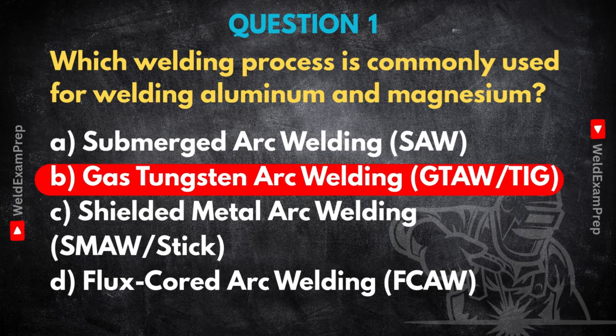Plus, for these reactive metals, that inert gas shield, usually argon, maybe helium, completely surrounds the weld pool, stopping oxygen getting in. It prevents that instant oxidation that would mess everything up. That oxide layer forms almost instantly otherwise, doesn't it? Instantly. And it's tough. So TIG prevents that. Now, if you think about the other options, SAW: too much heat, deep penetration, relies on flux. Not good. SMAW: less control, slag formation. Again, not ideal. And FCAW uses flux inside the wire, so you still have potential flux issues.